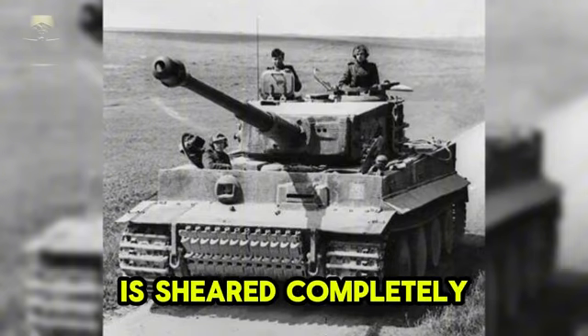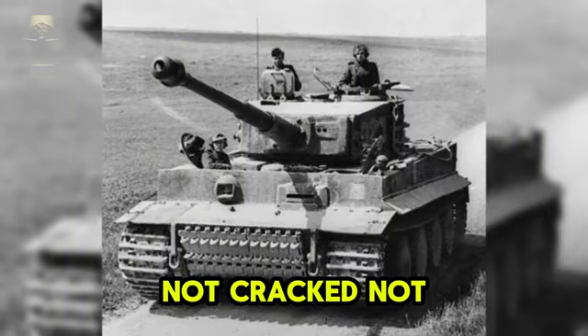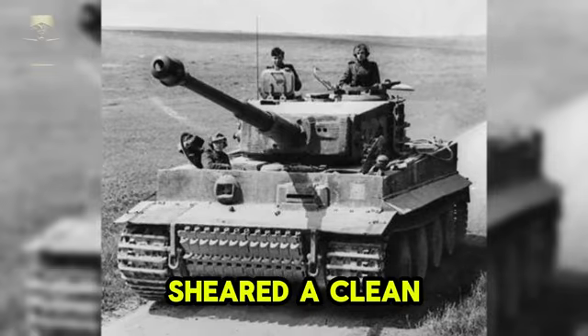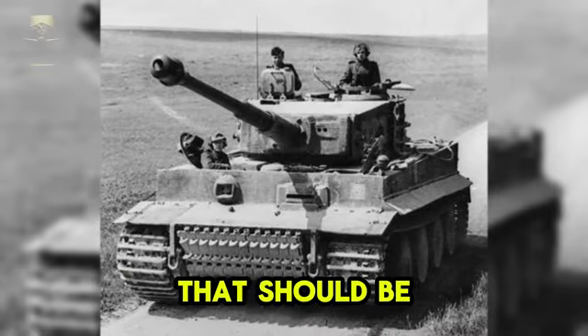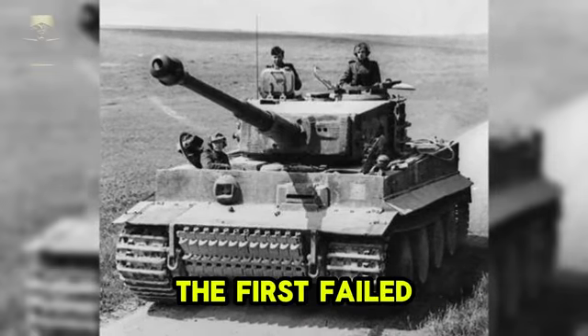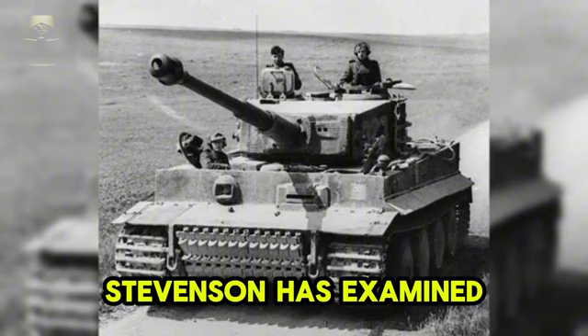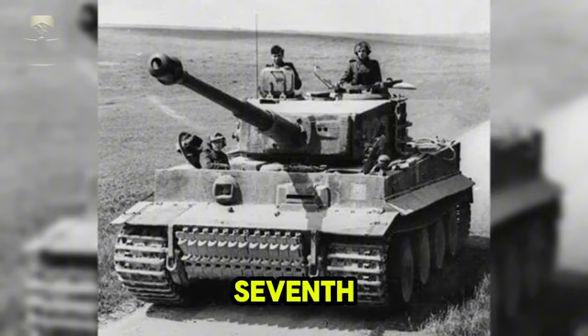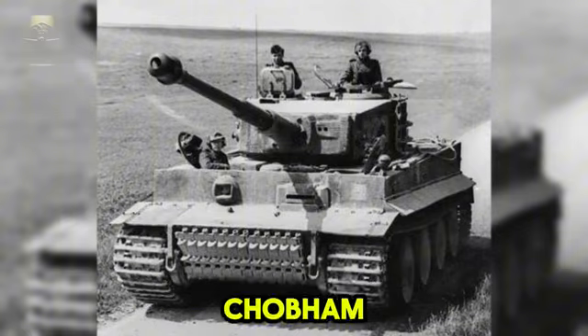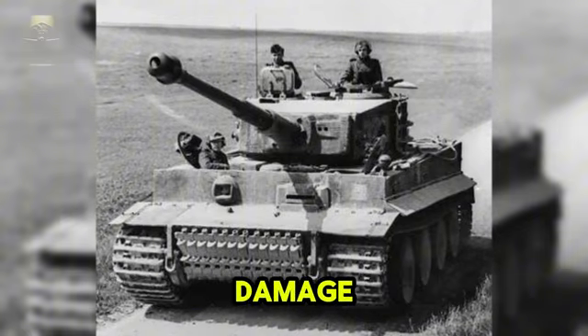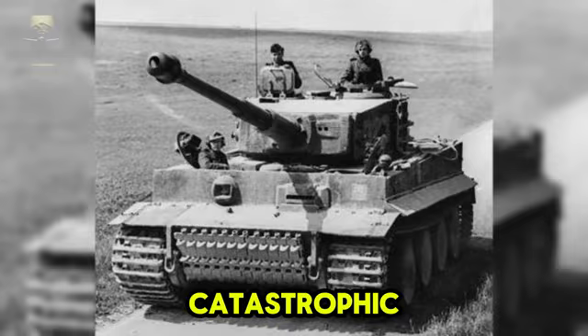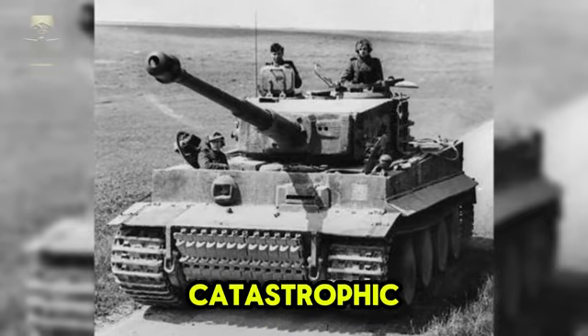The gear tooth is sheared completely off, not cracked, not worn, sheared, a clean fracture through hardened steel that should be nearly indestructible. This is not the first failed Tiger transmission Stevenson has examined. It is the 7th. Every captured Tiger tank delivered to Chobham arrives with transmission damage. Some minor, some catastrophic. This one is catastrophic.